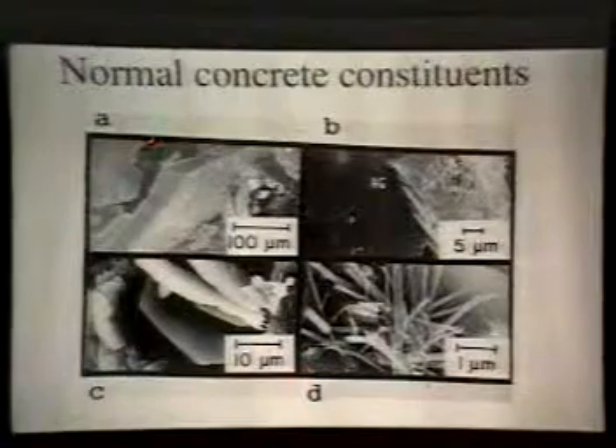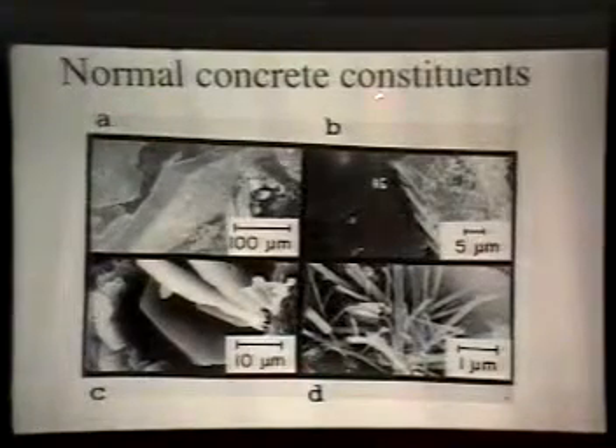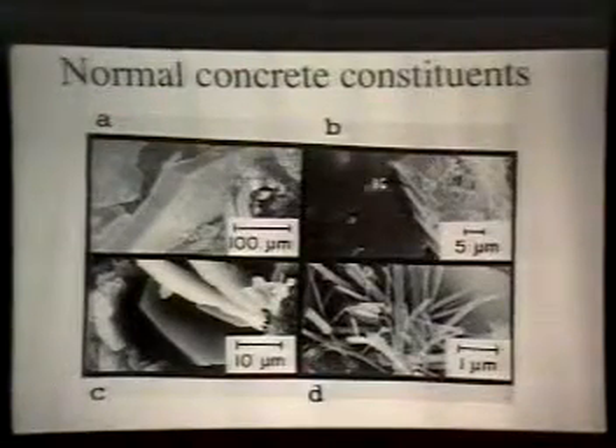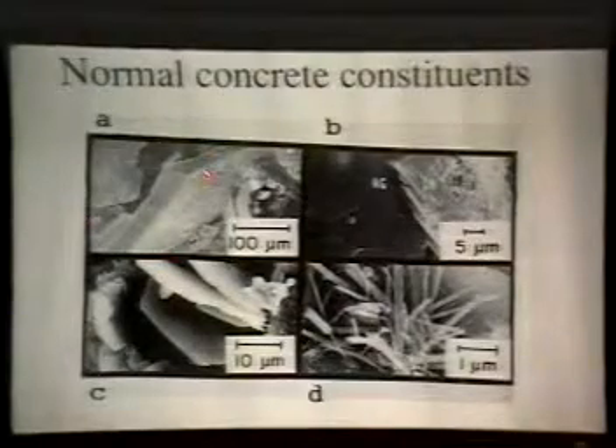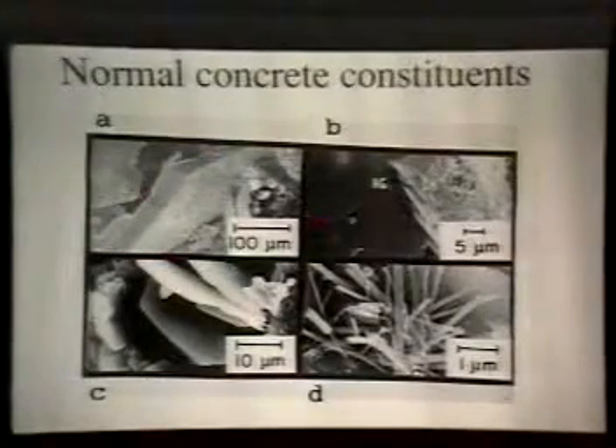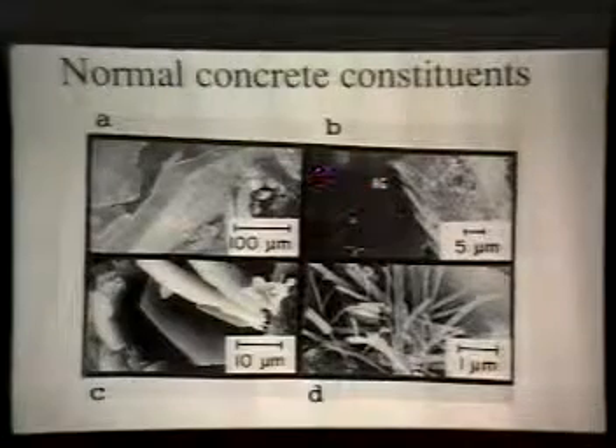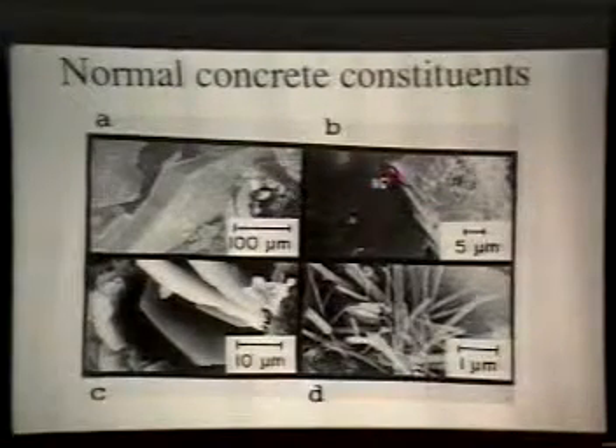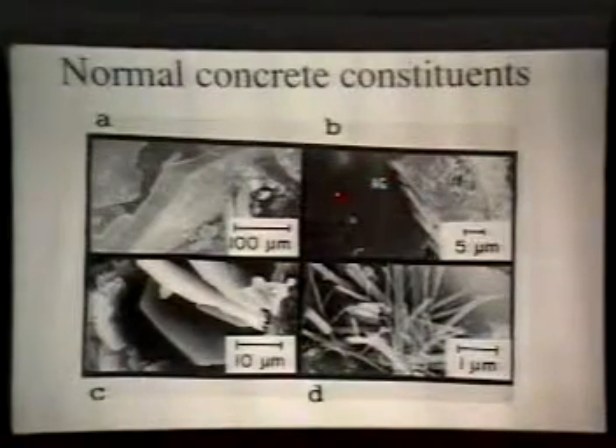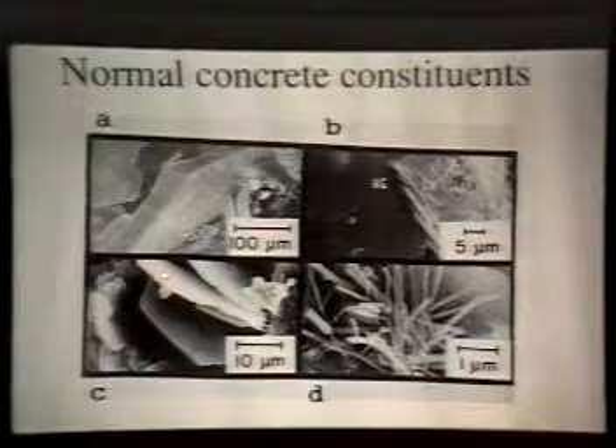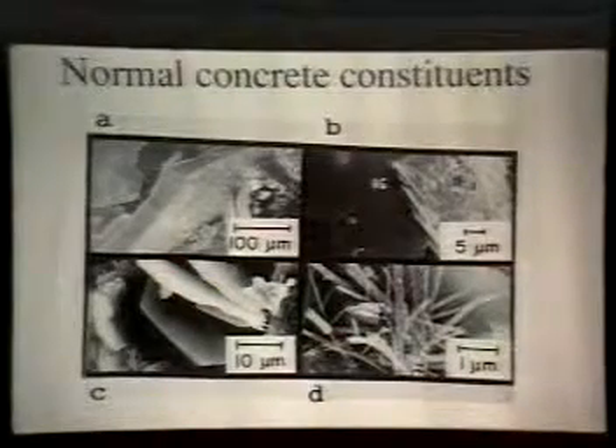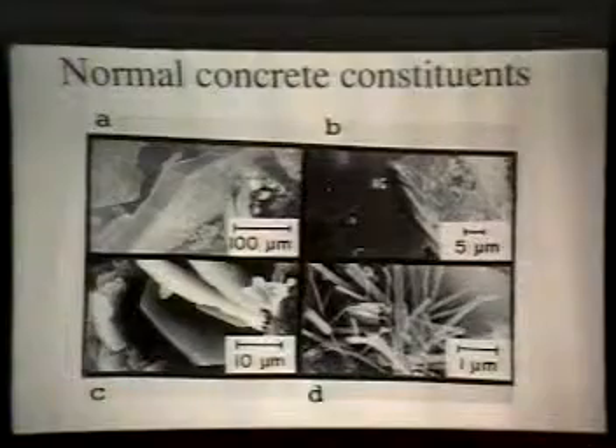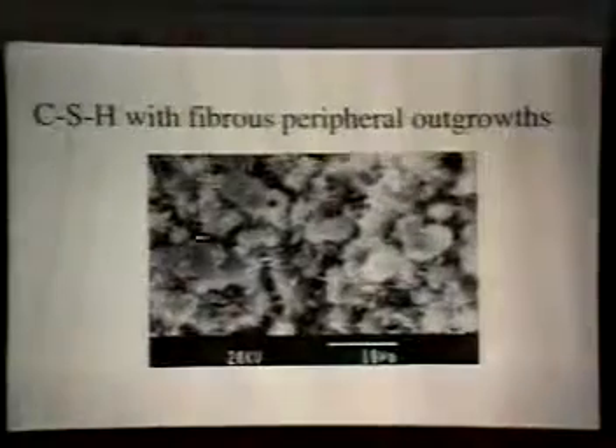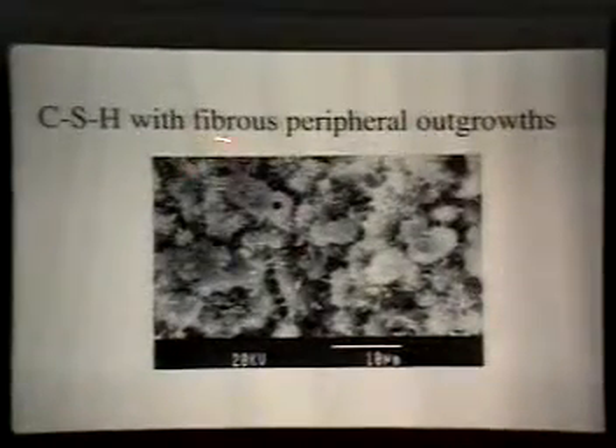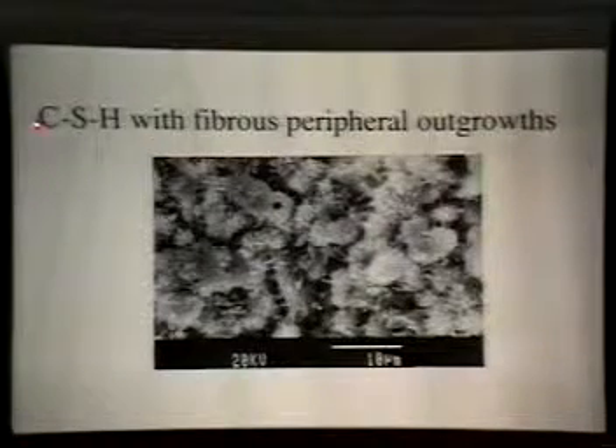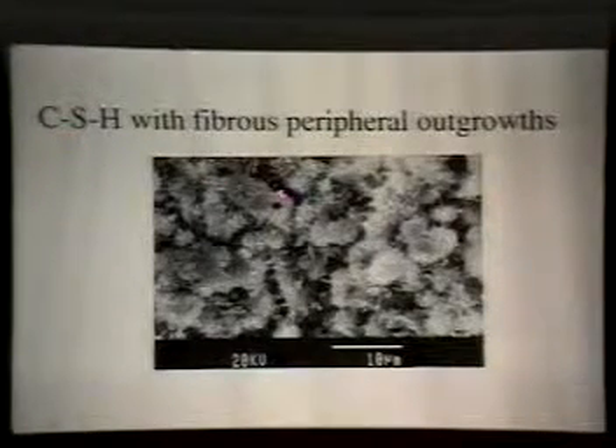Normal concrete constituents under the SEM would look like these. You have the lime crystals, calcium hydroxide, large chunky tabular crystals. You have the aggregate paste interface. This is your aggregate. You have the lime crystals oriented at the interface. You have the hexagonal crystals of monosulfate and some primary ettringite needles. And of course, you have the principal binder material, which is calcium silicate hydrate with its fibrous growth.